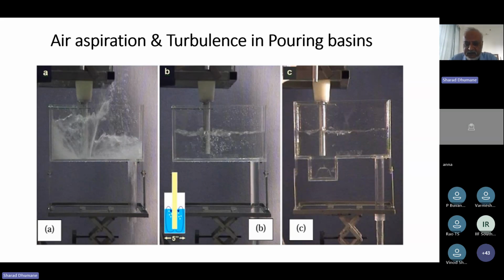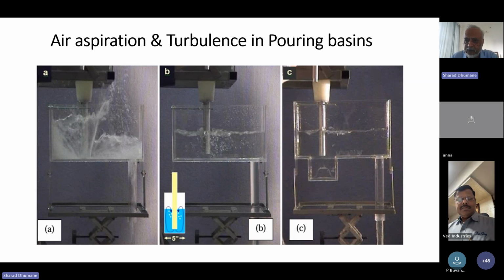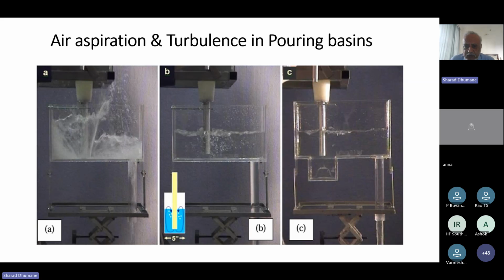The popular Campbell theory basically talks about these air bubbles or bifilms. This creates the source of the microporosity and pinhole porosity in our casting. So these are again related to your melt quality, because you have taken all those actions and safeguards before pouring, but during your pouring, there is a violent turbulent flow, and then your metal gets oxidized. That is called reoxidation, air entrapment, and it creates a risk of defects. These are more harmful because these defects lie subsurface and are opened after machining. So these are more harmful than your other defects.